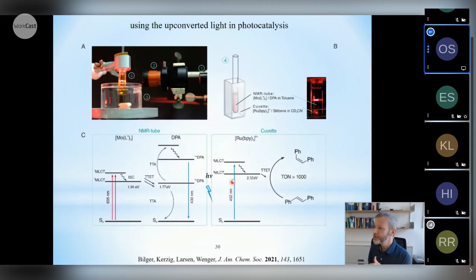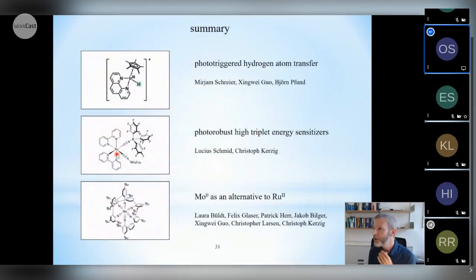So after radiative energy transfer, they had photoexcited ruthenium tris-bipyridine, intersystem crossing, and they used the triplet MLCT then to drive the photoisomerization reaction here of trans to cis stilbene. What I appreciated personally was the concept here of exploiting radiative energy transfer for photocatalysis, and also the fact that this thing was remarkably robust. The turnover numbers are really good. And many of the precious metal-based TTA upconversion systems that I know are not as robust as Jakob's molybdenum system here. So that's it, basically.